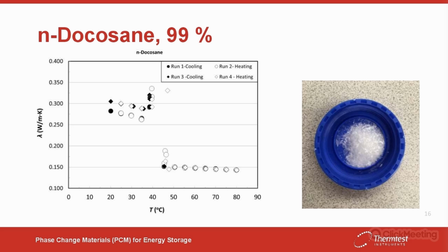Here we heated it up to 80 degrees, and while it was warm, from the bottom of the cell we poured the fluid inside, closed the bottom of the cell, and set the cell and the sensor inside the device. And then we ran measurements.